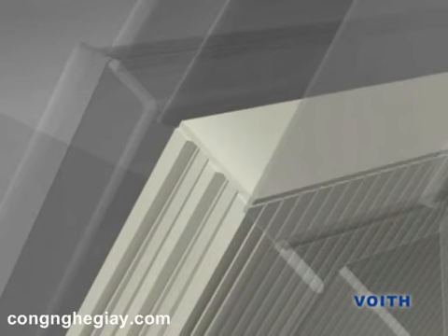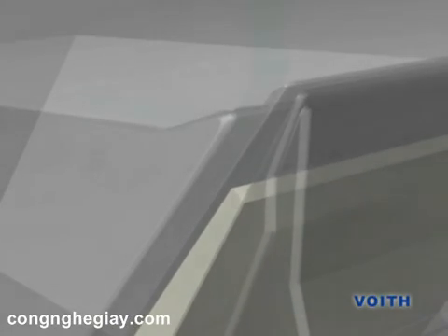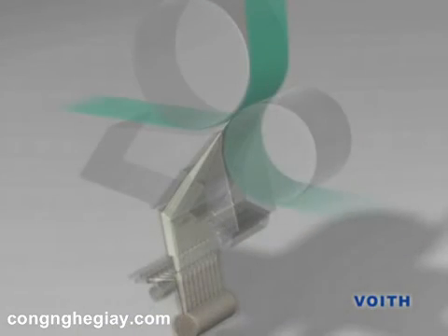In the head box nozzle, the suspension is then brought together again, accelerated to jet velocity, and brought onto the wire with a jet thickness of approximately 8 millimeters. By adjustment of the slice by fractions of millimeters, the jet angle and thus fiber orientation are controlled. The tensile strength of the paper can be controlled by specific regulation of the differential speed between jet and wire.